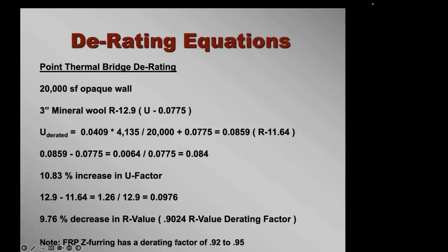Your FRP, from the different sites I've looked at, they're claiming 0.92 to 0.95. So we're really close to that with the brackets, and some people don't understand why. And I go, well, because from the same building, you need 10,000 linear feet of this continuous Z-furring, where you only need 4,135 brackets there when you're doing the calculation.